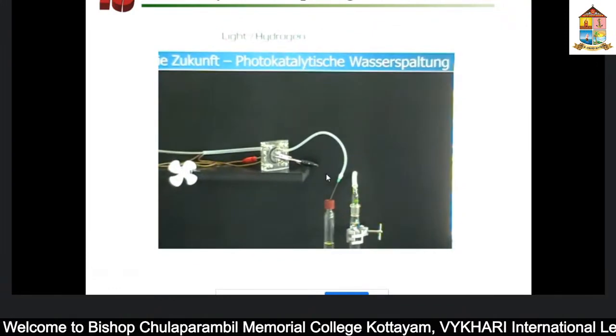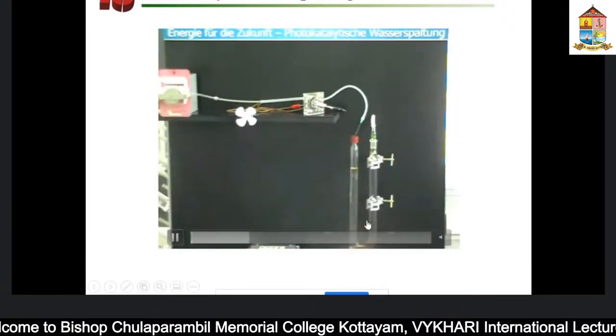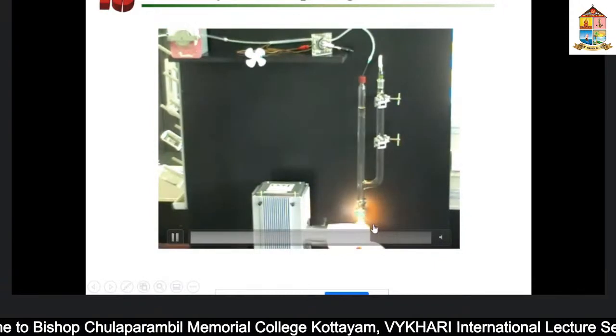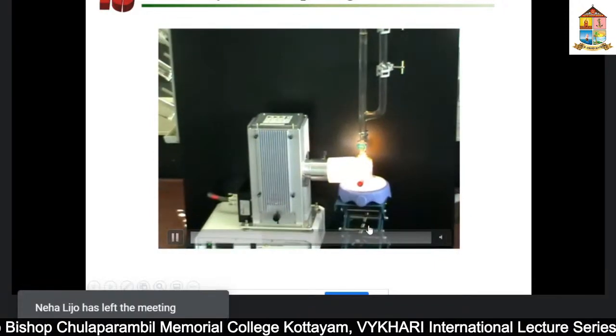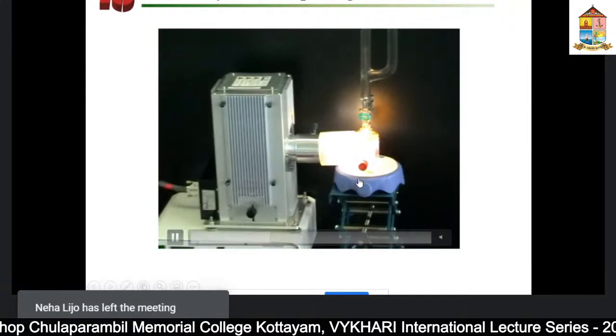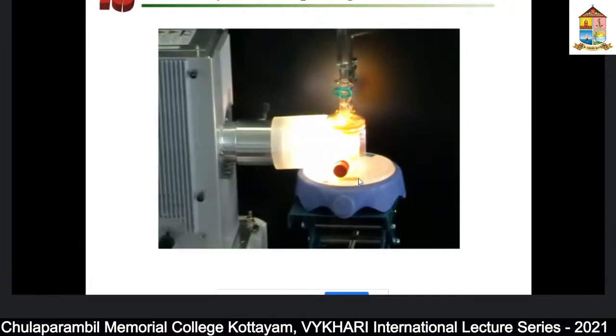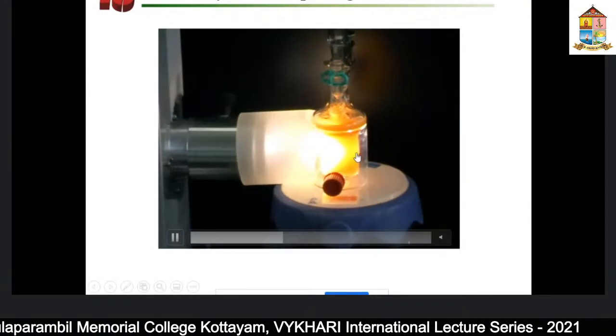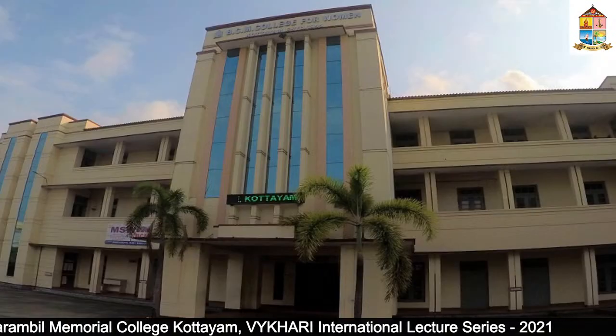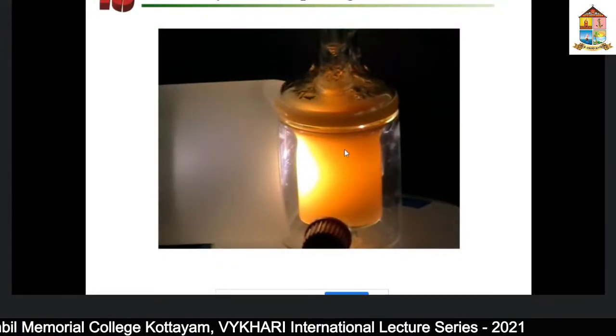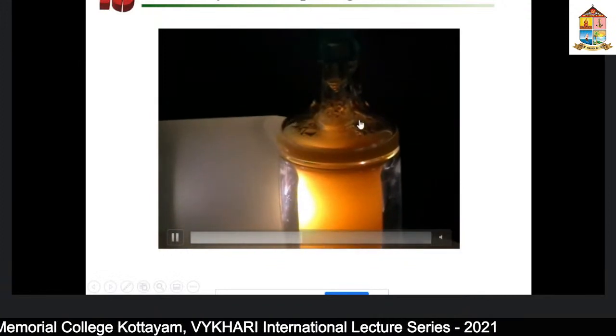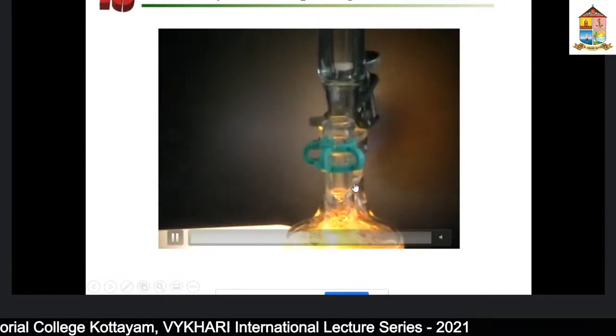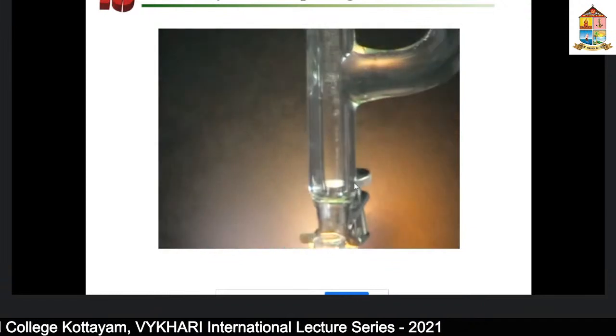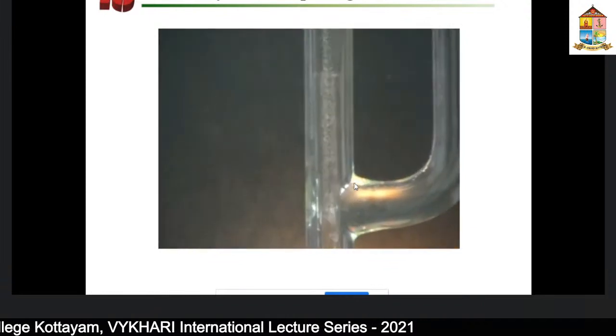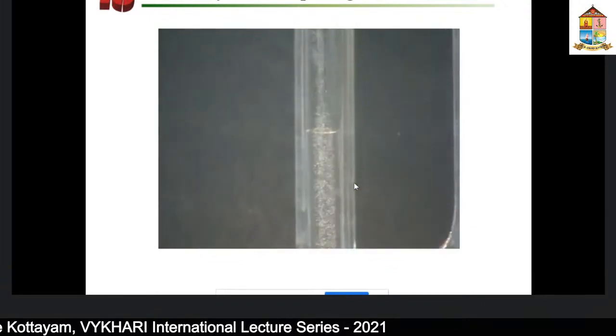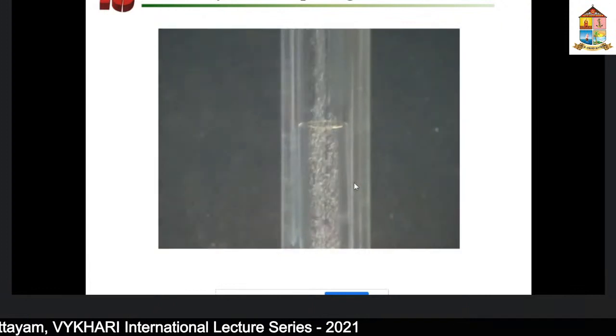What is important is that this reactor should contain a water jacket. So this should be consistently cooled down, or kept at constant temperature, probably room temperature, because with this intense light the water can boil, which already mediates the hydrogen production as well. So one should remember that. This is a very simple reactor. You don't have to make any fancy reactor for this. You just have to have one neck, or maybe three necks, because two are for the water jacket, and one for the collection of hydrogen. That's enough.